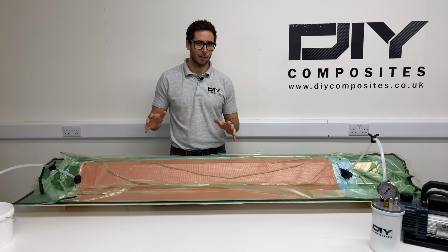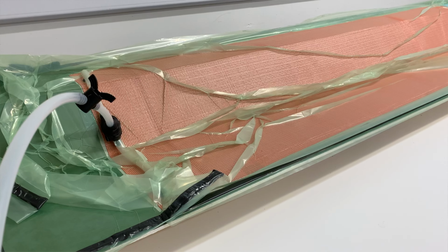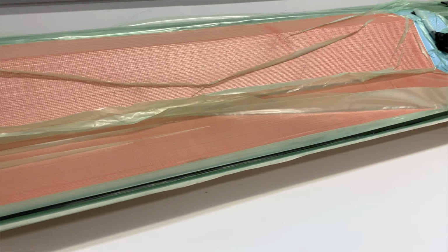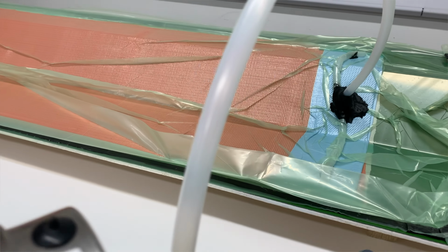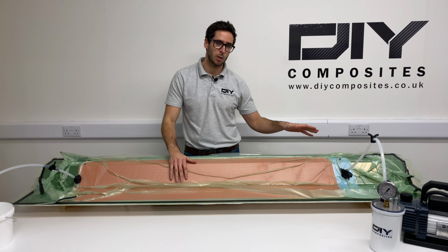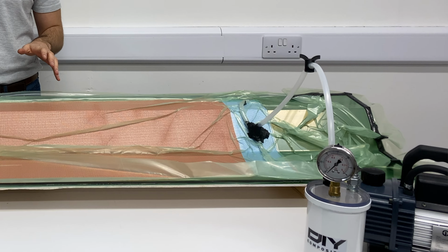We've now drawn full vacuum on our bag. We've made sure that we have enough bagging material into the corners so that the laminate is really consolidated against the mould. We did have a leak over here, which we've sealed with TT150 bagging tape, and now we have